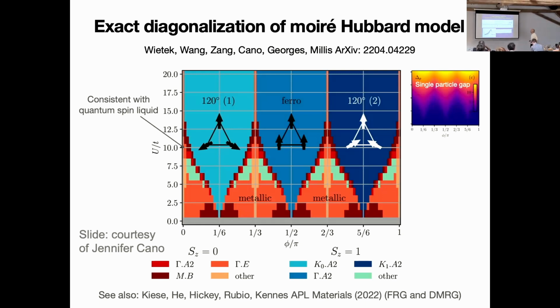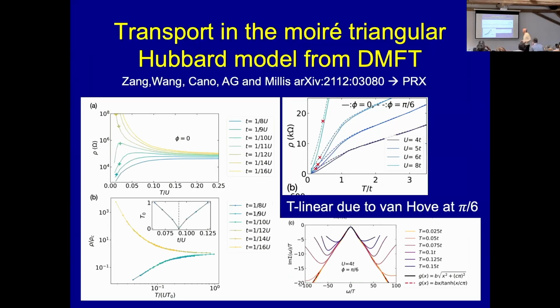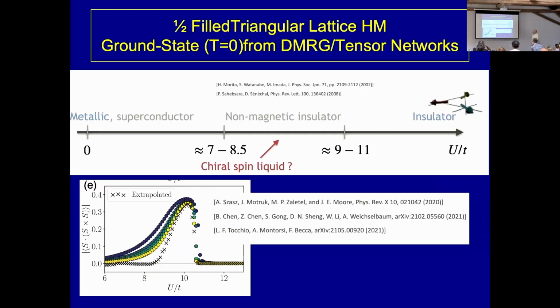Well, this problem was studied in a set of beautiful papers just a few years ago, like 2 years ago, in particular by Mark Zaletel and his group. What he showed is that this model has a phase transition at 0 temperature between a metal and an insulator, but this transition is not directly from a metal to the 120-degree ordered insulator. There is clear evidence that there is an intermediate phase in the range of coupling between about 8 and about 10, into a non-magnetic insulator phase.